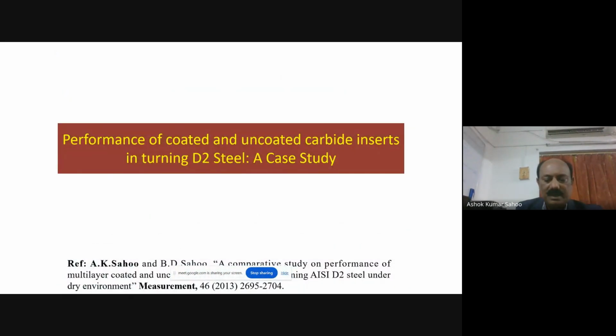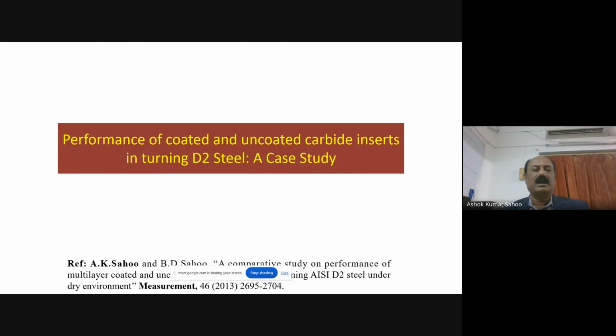These hard thin-layer coatings are titanium nitride, titanium carbide, titanium carbonitride, and aluminum oxide. And these coatings are provided in the range of 2 to 15 microns of thickness on the cutting tool by means of physical vapor deposition and chemical vapor deposition techniques. I am just showing one case study comparing the performance of uncoated and coated carbide inserts during machining of a hard material, D2 steel.